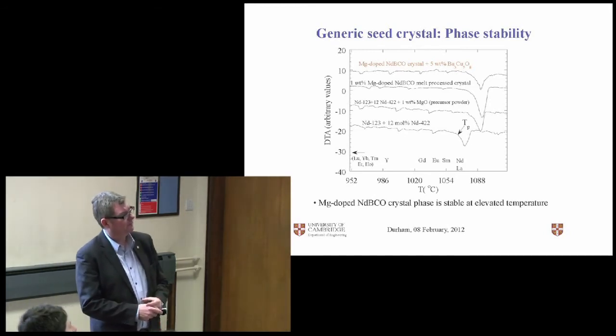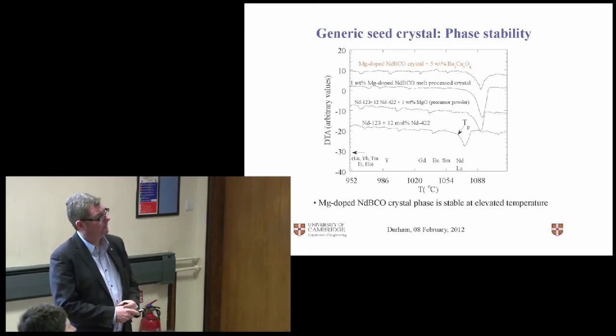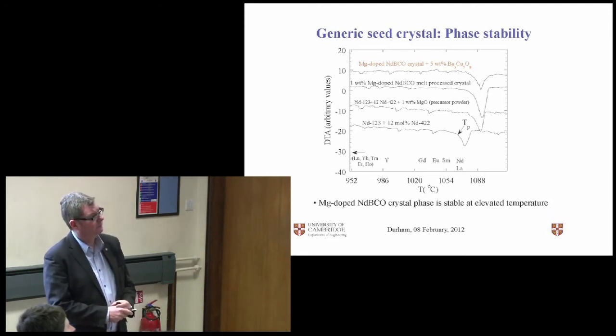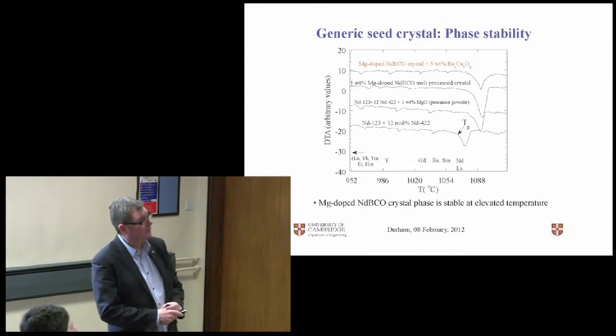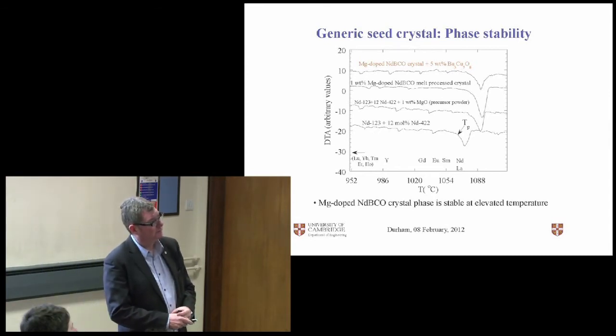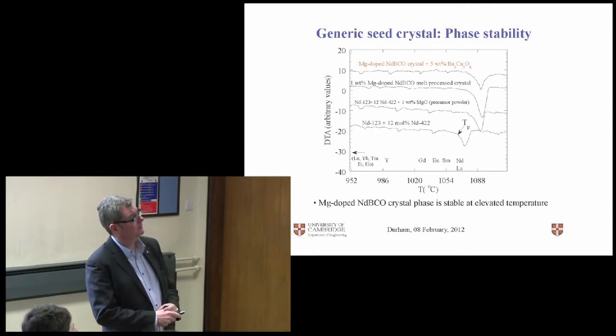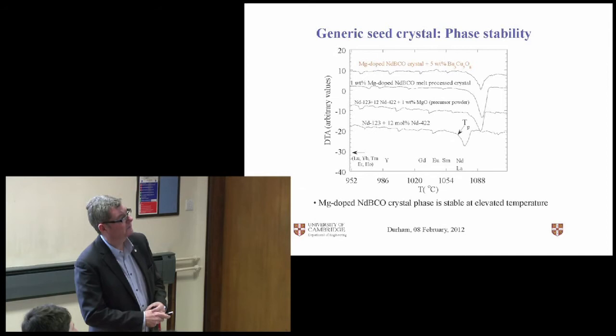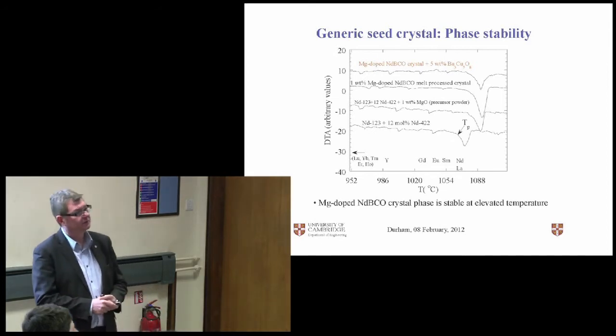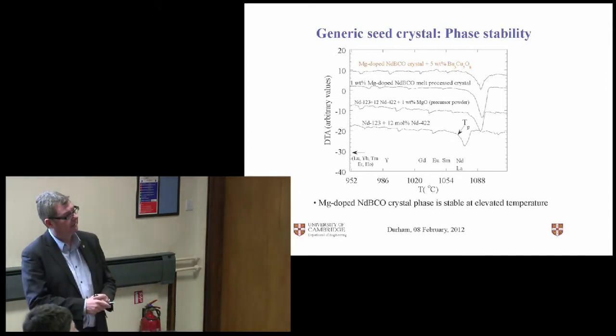Okay, this looks at the phase stability of the magnesium doped neodymium barium copper oxide. So we've taken a variety of conditions. So here's straightforward 1, 2, 3 with its low decomposition temperature. If we then add magnesia as a precursor powder, there's some pre-reaction, and immediately the decomposition temperature increases. We then put 1 weight% magnesia in our crystal, we melt process it, and then we look at the DTA of the crystal, and again the temperature is high.